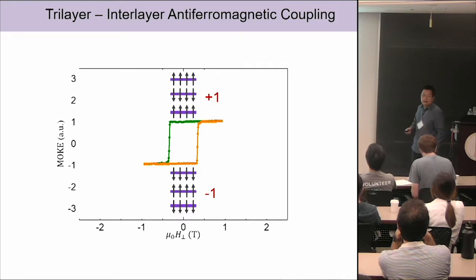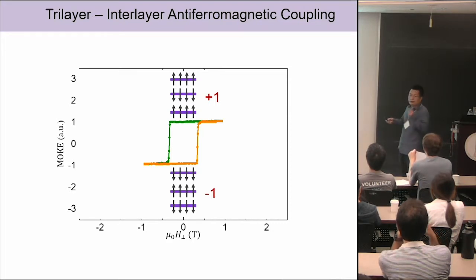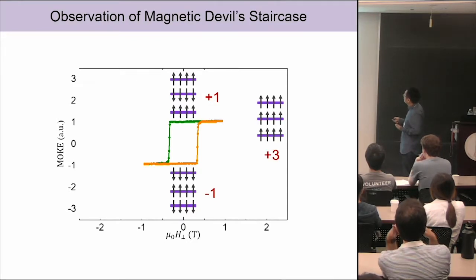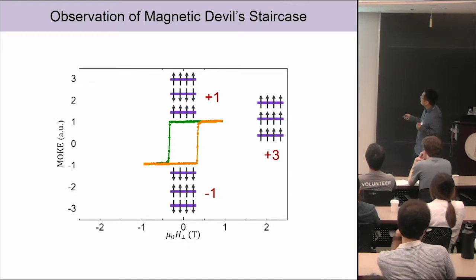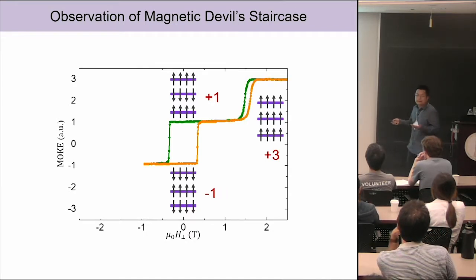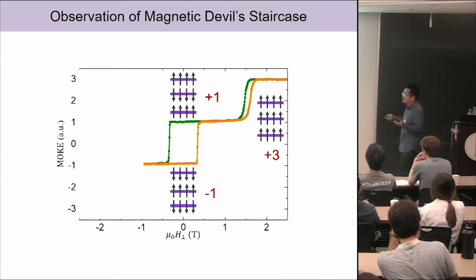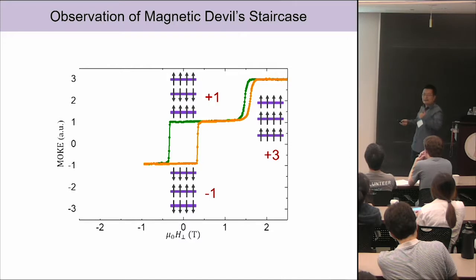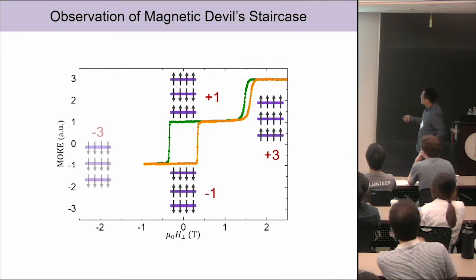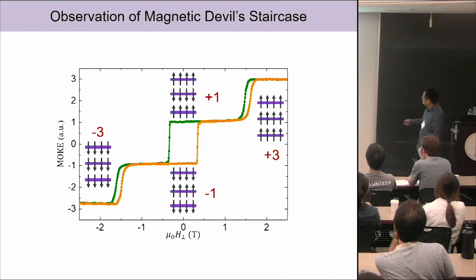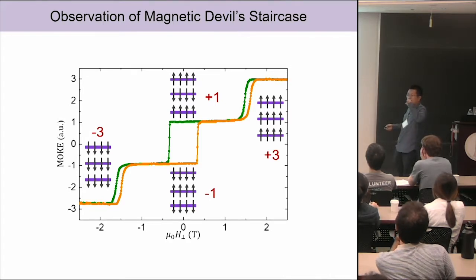Then without any calculation, you know the Kerr rotation signal ratio from the top state to the bottom state should be around 1. That's exactly what we see. Then you can convince yourself: if you apply a magnetic field to align all the spins in the same direction, you count the total magnetization, and it should be 3. Then the ratio of the Kerr rotation signal to these ground states should be 3 to 1. That's also what we see. So this is a very simple and easy way to understand the magnetic states just by measuring the Kerr rotation signal. The other one is around minus 3. Each step shown here is a spin flip transition; basically, one layer flips its magnetization.